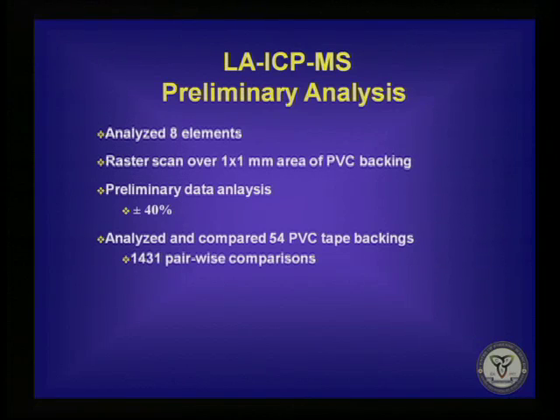We analyzed 54 of the 78 electrical tapes, and that represents 1,431 pairwise comparisons. And we did some initial reproducibility studies. So for a number of tapes, we did repeat measurements. For one particular tape, we looked at 17 samples from that tape. And when we applied the plus or minus 40% criteria, there were only two pairs that were falsely discriminated based on only one element, zinc.